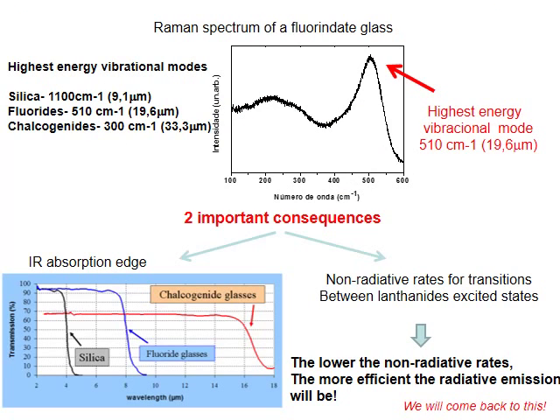The multiphonon edge is not the only property that will depend on the vibrational mode's energy. In this figure, we have the Raman spectrum obtained for a fluorindate glass. The harmonics of the highest energy vibrational modes are the ones that will define the absorption edge, as we have already said. The other important consequence that we will explore in next sections is the depopulation or deactivation of electronic excited states. Vibrational modes will define the non-radiative transition rates between excited states in lanthanide ions, for example. The lower the energy of the vibrational modes, the lower the non-radiative decays will be.